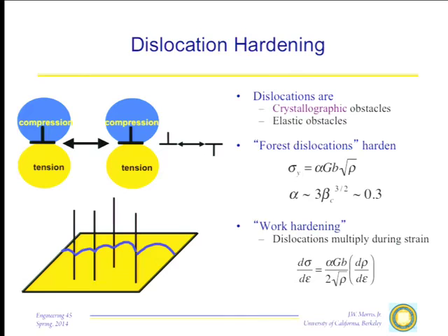So the dislocations annihilate. This process, dislocation annihilation, of course causes rho to go down and causes the strength to decrease. And in a couple of the laboratory experiments that you did, when you observe recovery, you observe materials get softer as you anneal them. Part of that might be grain growth, but also a good part of that is that if you heat a material up to high temperature and hold it there, if you anneal it, the dislocations interact with one another, they align and they annihilate. So the dislocation density comes shooting down, and as the dislocation density comes shooting down, the yield strength does as well. So this is a major softening step, this dislocation annihilation.